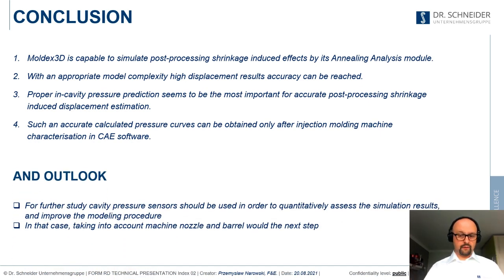But can we do anything better? Yeah, of course. We can also model the machine nozzle and even the whole barrel to introduce additional pressure loss in our system and to see how the results are getting better. They should be. But the real thing would be if we can compare the simulated pressure curves, simulated pressure values from our cavity with the reality. So the final checkup would be to install pressure sensors in our mold and then compare the simulation with the real pressure curves and try to improve it.